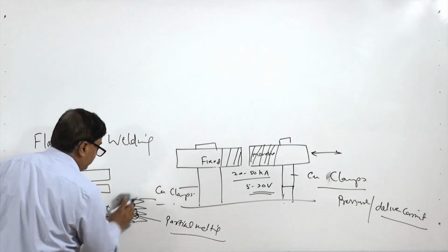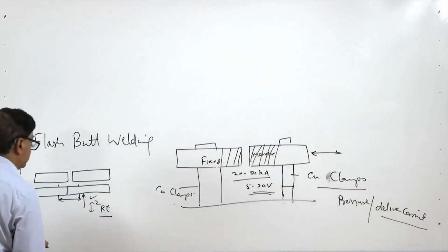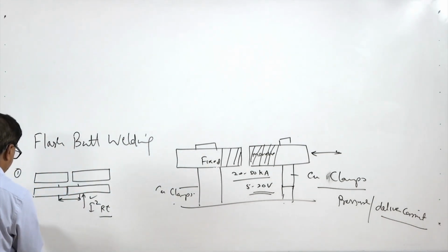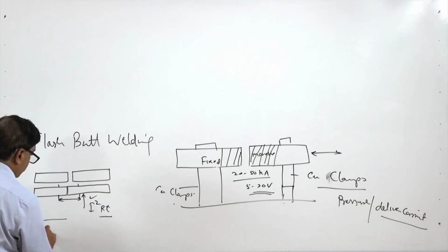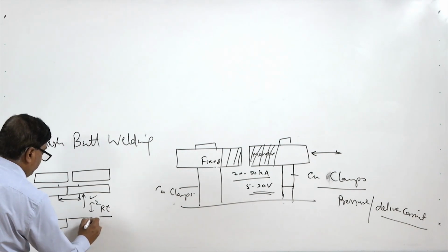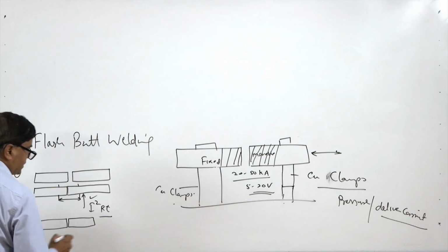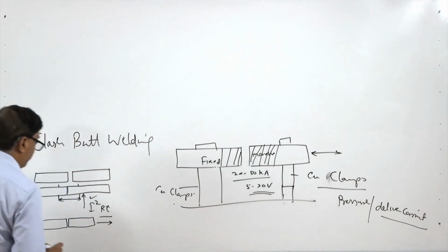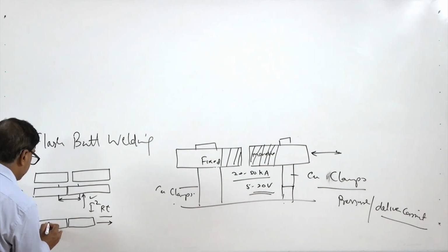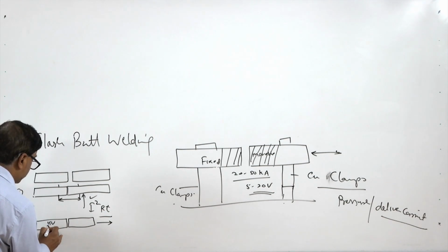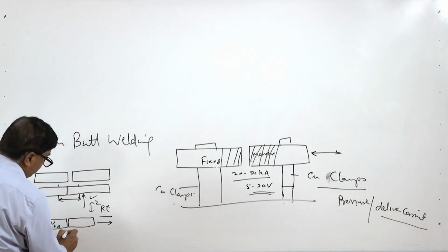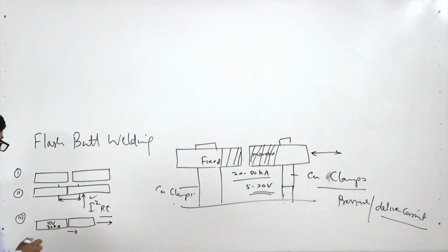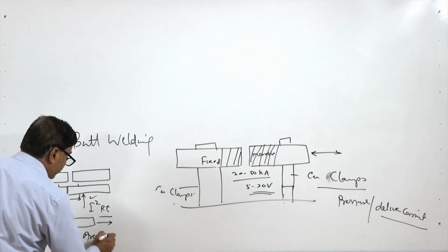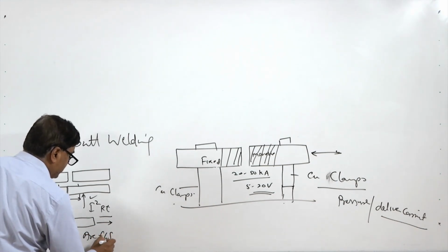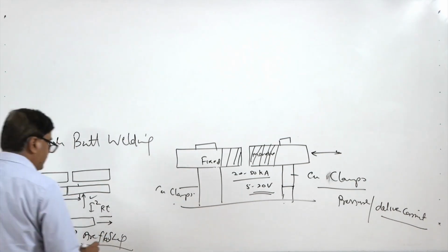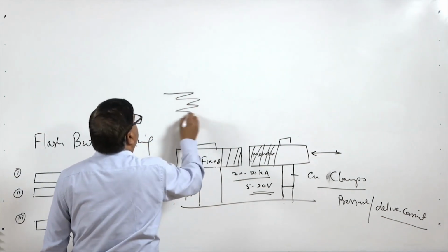So, after this preheating, in stage 2 they were brought into contact. In stage 3, in a very controlled way, the members are moved apart. Since there was a voltage of say 15 volt and flow of current of say 30,000 ampere, as soon as the movable component starts moving away, we will see that heavy arcing or flashing starts.